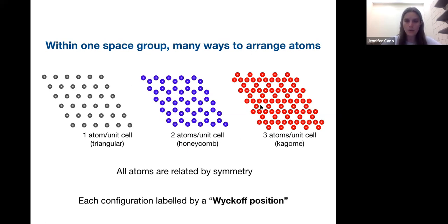And the other important point is that once you have one of these configurations, all of the atoms are related by symmetry. So for the triangular lattice, it's obvious each atom is related to each other atom by a combination of translations. But in the honeycomb lattice, half the atoms are related to other atoms by translations. And then the other half, you need to first do a six-fold rotation to swap sublattices and then do translations. So in any case, all atoms are related to all other atoms by some combination of symmetry operations. And you can classify each of these by the group of symmetries that leaves one atom invariant.